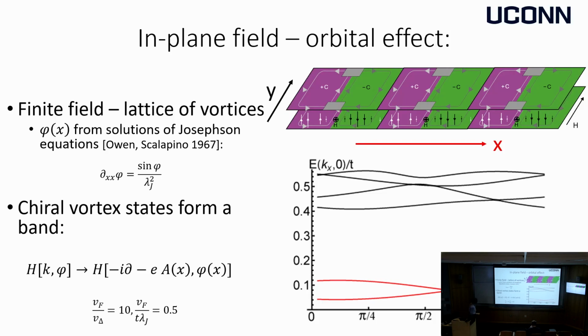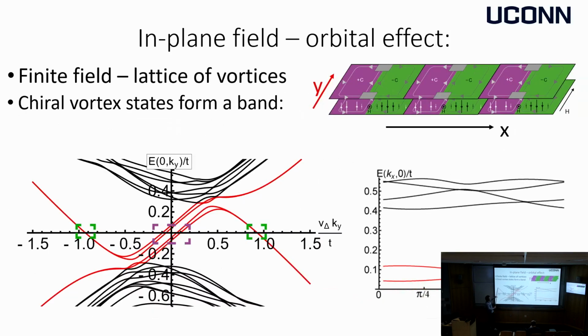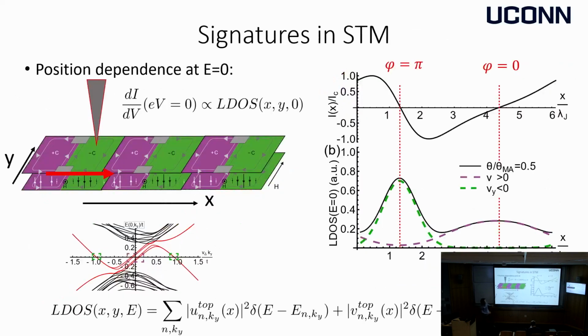So if you consider a vortex lattice, like an infinite system, you can actually calculate the band structure of quasiparticles in the system, and you find that there is a band of those vortex modes that's separated by a gap from the rest, from the bulk, and that band is chiral in the sense that you can see the dispersion along the y direction, there are distinct states dispersing in one direction and the other, and those states are actually localized. So let's look at this one. That's the green one. If you plot the density of states, they are localized at one position where the current vanishes. And if you look at the states dispersing in the opposite direction, they're at the nearest neighbor position.